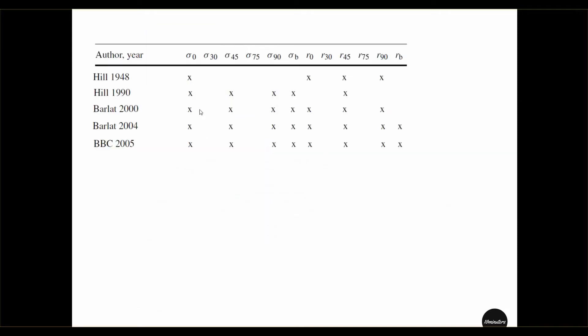So far I have explained how to get yield stresses and Langford coefficients using uniaxial tensile testing. For biaxial points you will need some sort of biaxial test or bulge test. However, there is a workaround: you can use Hill 48 or Barlat 89 predictions for the biaxial yield point and biaxial Langford coefficient without doing the experiment. They will not be very accurate, but at least you get a prediction that you can then use to calibrate the parameters required for BBC05.